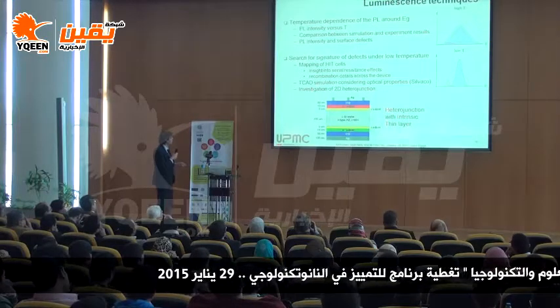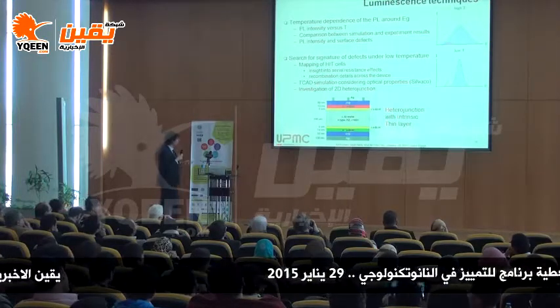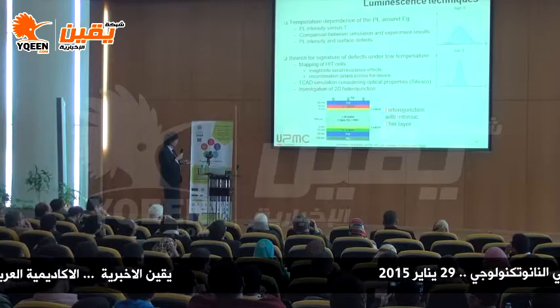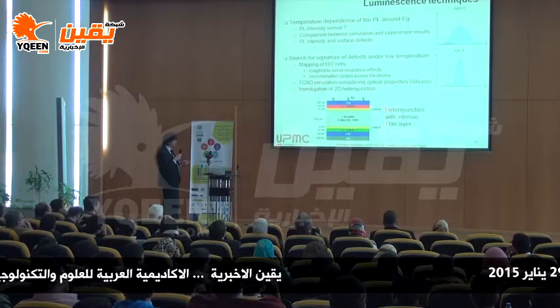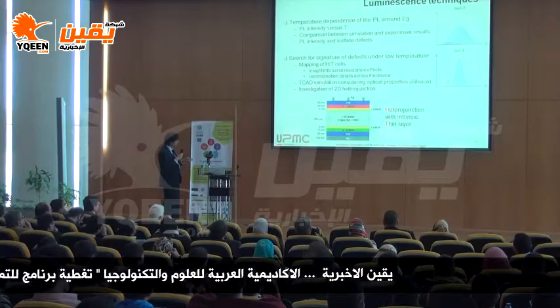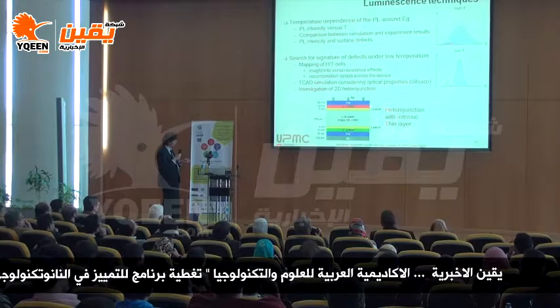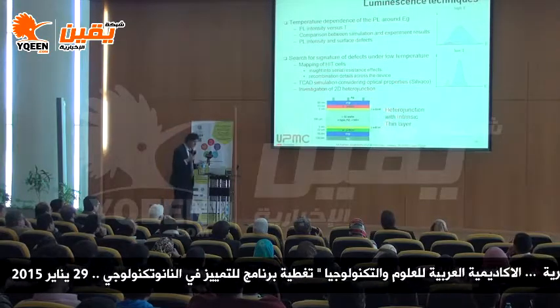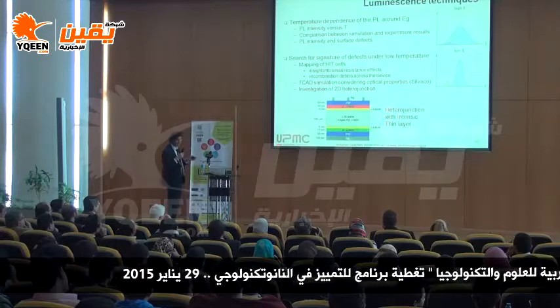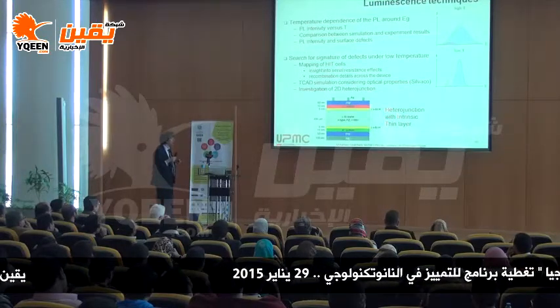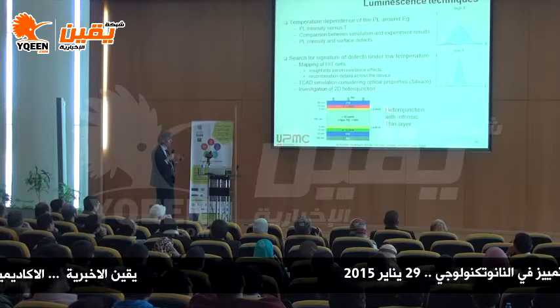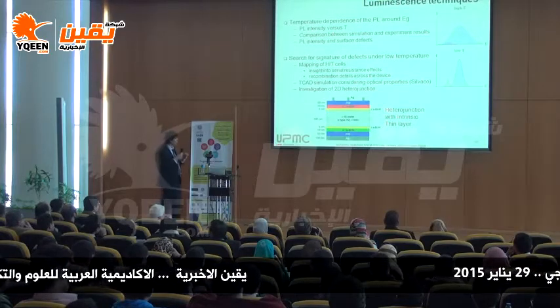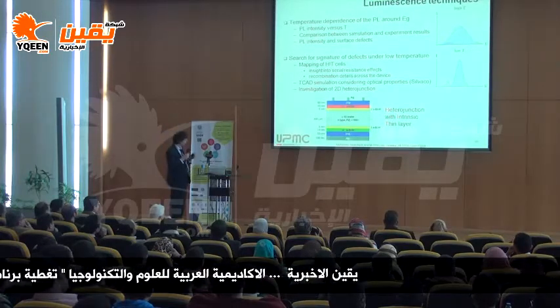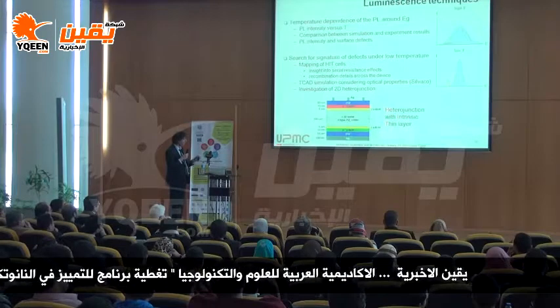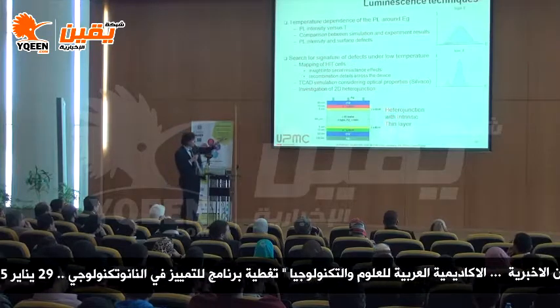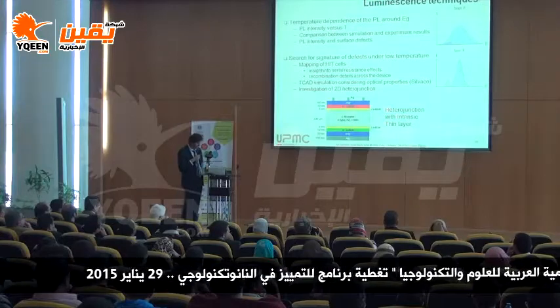So these are typical devices that we look at. Here you can see the top electrode, which is ITO. Later on I will mention graphene. One of my projects is to get rid of this electrode and replace it with graphene. But although the transparency is okay, optically it's fine, the electronic properties are still rather poor, and we need to develop a doping strategy to increase the carrier number inside the graphene to be able to be competitive with ITO. So far it's not.